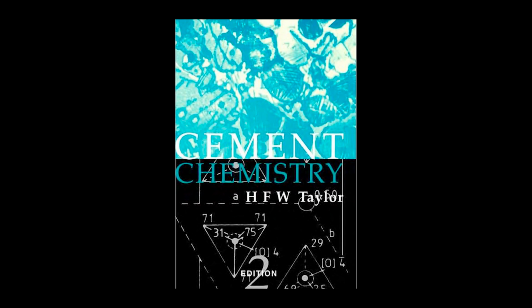And we learned that cement is not a static material. It is a living, meticulously engineered system defined by kinetic and thermodynamic compromises. Whether it's using superplasticizers to manipulate the zeta potential of individual grains, or ensuring that supplementary materials like slag form stable hydrotalcite instead of destructive periclase, every single detail is a calculated risk.